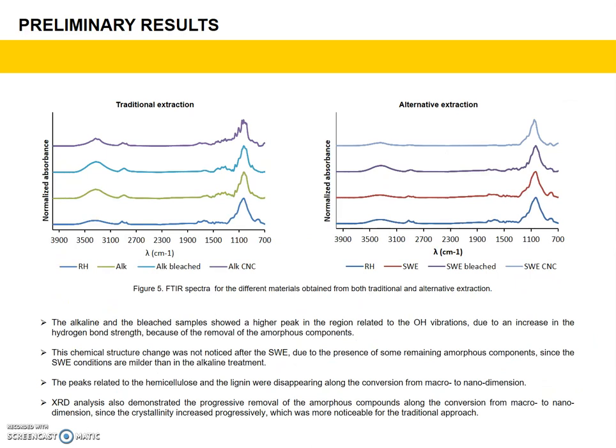Regarding the FTIR analysis, the alkaline and bleached samples show a higher peak in the region related to the OH vibration due to an increase in the hydrogen bond strength, because of the removal of the amorphous components. This chemical structure change was not noticed after the subcritical water extraction due to the presence of some remaining amorphous component, since the subcritical water extraction conditions are milder than in the alkaline treatment. The peaks related to the hemicellulose and the lignin disappeared along the conversion from macro to nano dimension. XRD analysis also demonstrated the progressive removal of the amorphous component along this conversion, since the crystallinity increased progressively, which was more noticeable for the traditional approach.